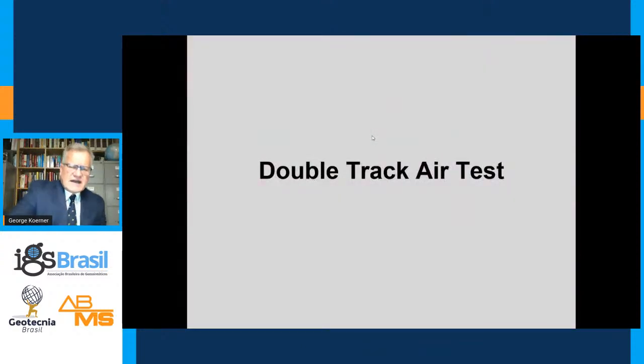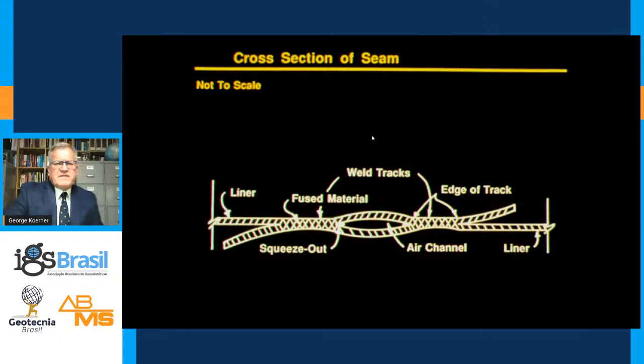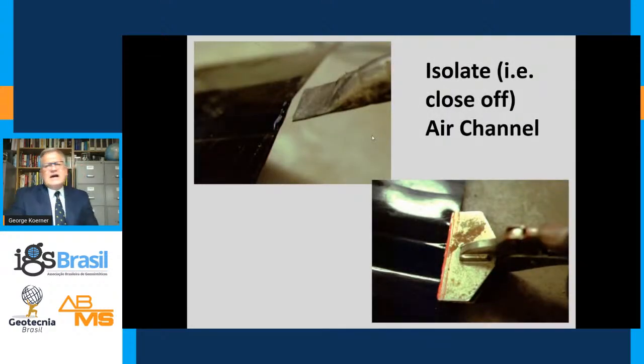The Double Track air test is certainly the premier test. You've seen this cross section before, and that air channel is very important to the success of this test, and it certainly needs to be open and clear. You need to isolate the air channel, and you do that by closing off the two ends. That's typically done with hot air, Leister seam, and wide mouth vice grips.